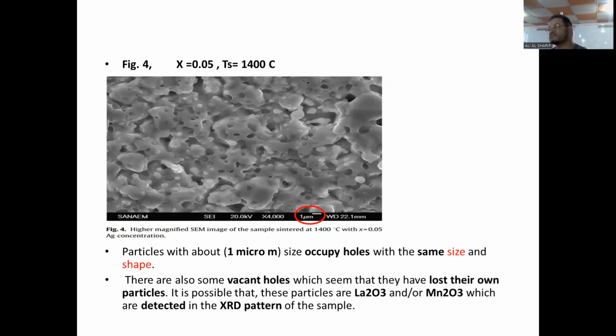These particles have some characteristics. We can't say it's an advantage or disadvantage, but they have some characteristic, because these small particles, approximately 1 micrometer, can attract the holes with the same shape and size. There are also some vacant holes, which suggests they have lost their own particles. That means some holes will maybe be empty, as they have lost their own particles. It is possible that these particles are lanthanum oxide, manganese oxide maybe, which are detected in the X-ray diffraction pattern of this.